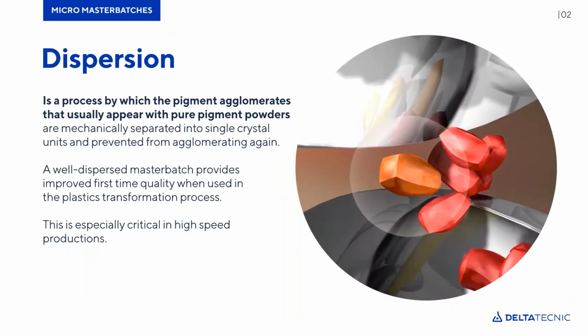So dispersion, to summarize, is the process by which the pigment agglomerates that usually appear with pure pigment powders are mechanically separated into single crystal units and prevented from agglomerating again. And a well-dispersed Masterbatch provides improved first-time quality when used in the plastics transformation process. You get maximum color strength out of the Masterbatch when the Masterbatch is well dispersed. And again, this is something that is 100% a responsibility of the Masterbatch manufacturer.